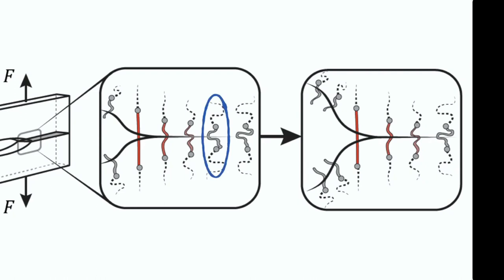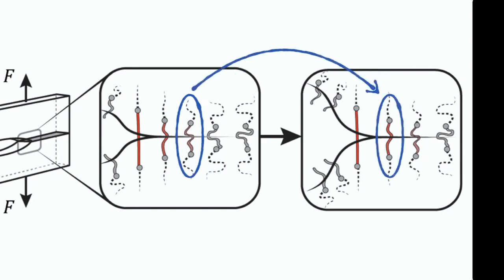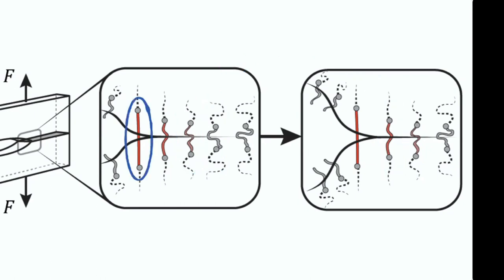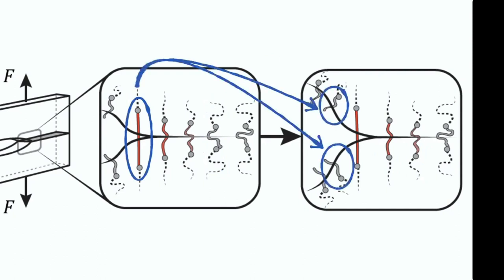And so if I start with a polymer that starts off a ways away from the edge of that crack, as the crack moves, now that polymer chain stretches a little bit. One that started out a little bit more stretches further still. And there's one that was right at the edge of that propagating crack tip, that as the tip moves, it actually broke through a covalent chemical reaction where bonds are being broken, as Patricia introduced. And so this macroscopic physical process of polymer networks wearing down and no longer being useful really boils down to molecules stretching to their limits and then breaking.